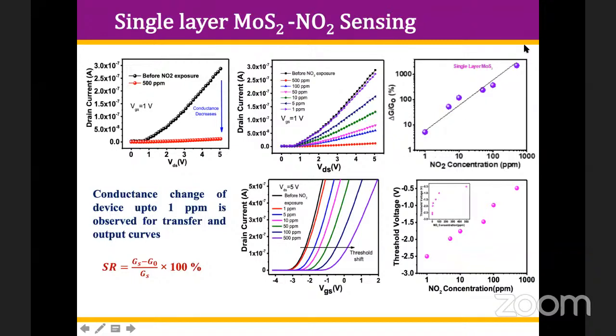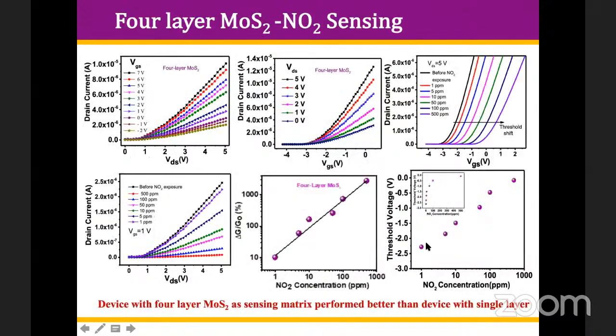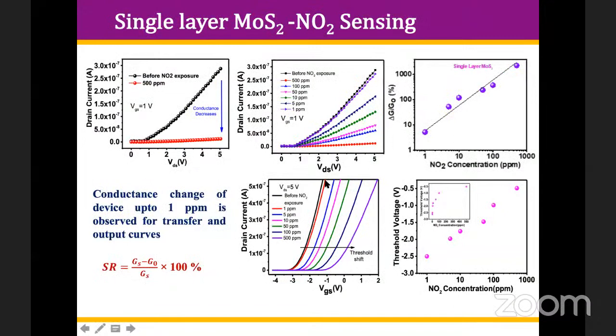And these are the calibration graphs with NO2 concentration, you can see. And here the shift in the threshold voltage also you can calibrate as a function of NO2 concentration. The choice is either you can go ahead with the conductance, or you can go ahead with the threshold voltage as a function of NO2 concentration, and we can obtain the gas sensing response. These are the studies with one layer, or you can say, monolayer of MoS2.